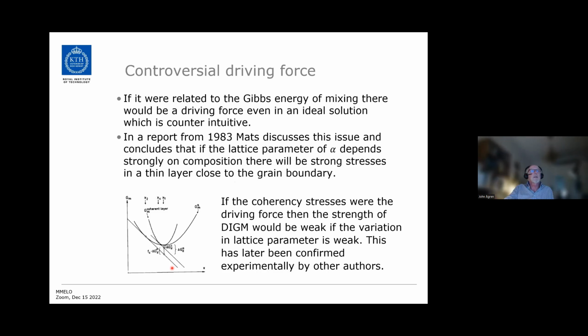Okay, so then he discussed this issue more, and he concludes that if the lattice parameter of this phase [varies with composition], stresses arise at the grain boundary. And those can actually be a driving force for moving the boundary. And that means that if there is a system where the dependence on the lattice parameter with composition is not so strong, you would not see DIGM. And this has to some extent been confirmed experimentally by other authors.